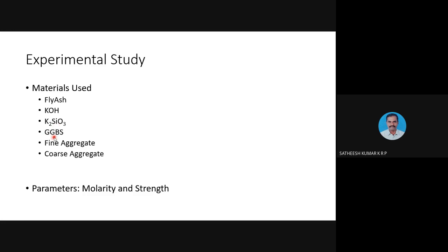And this GGBS was crushed, and only the fine particles passing 90 microns were used in this particular study. And the fly ash which we used was class F fly ash. We were not able to get access to class C fly ash, so we are using class F fly ash, which conforms to ASTM C618. And this fly ash mainly contains silicates.